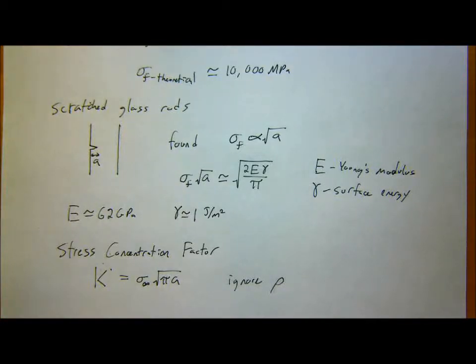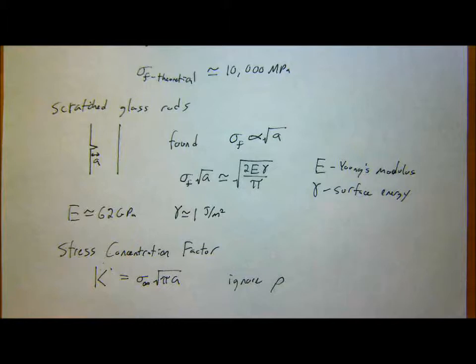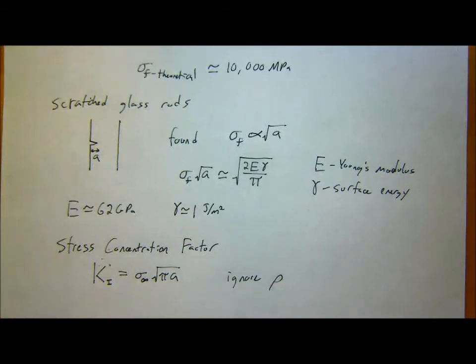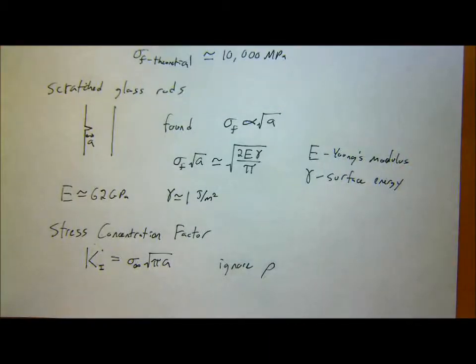You'd have to go into the microscope, probably an electron microscope if it was a really fine crack, which of course they didn't have back in those days. And even then, there's some ambiguity in terms of exactly what the radius is. So this is just a difficult quantity to figure out. So instead, we're only going to think about this in terms of the length of the crack, that length A. And more specifically, when we talk about stress concentration factor, we're normally referring to the mode one stress concentration factor. Remember there's those three fracture modes. This is, again, the most common one for materials. Technically there's also a mode two and a mode three stress concentration factor, but for the most part, we're just going to be thinking about this in terms of our mode one failure.